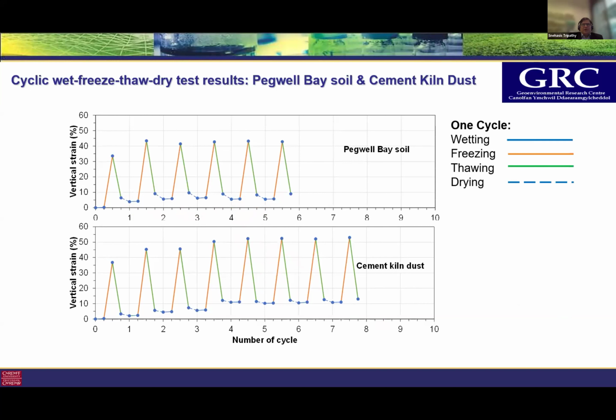The other important thing to note here is that materials which did not exhibit any swelling and shrinkage strain during wetting and drying cycles can exhibit frost heave and thaw settlement. Now, this is very important, since simply using industrial waste without checking its response to various climatic processes may not be ideal for designing resilient geoinfrastructure.